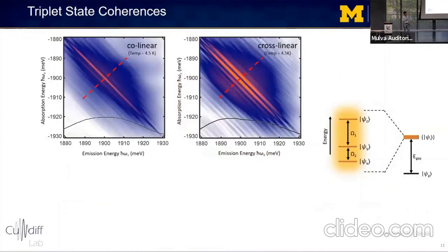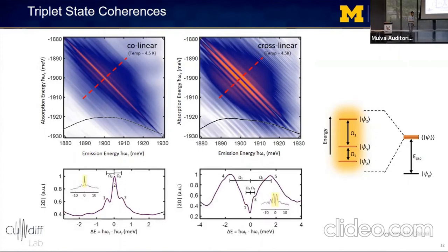So this is what the 2D spectra look like for collinear and cross-linear polarization. There's a lot going on here, but here we're just interested in what changes between the different polarizations, since this is what has to do with the triplet states. So to take a closer look, we can take cross-diagonal slices along this red dashed line, and we can see that the main differences are these peaks in the middle, which correspond to absorption and emission in and out of different triplet states. So let's start with the collinear spectrum.